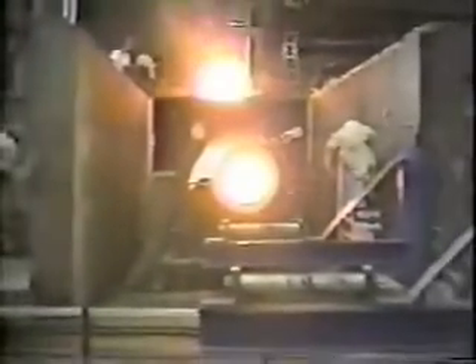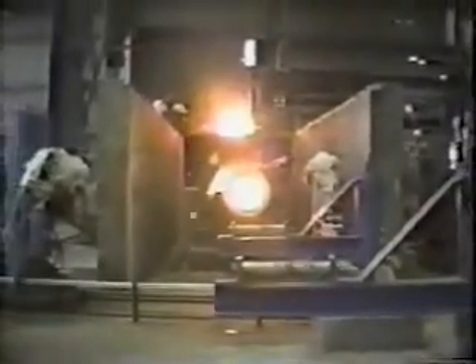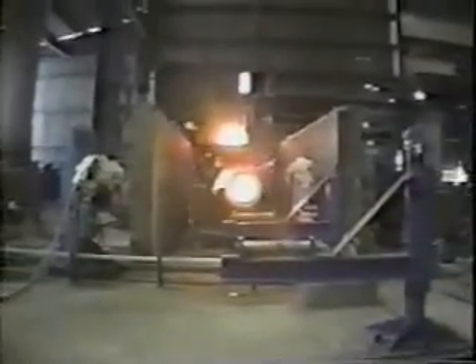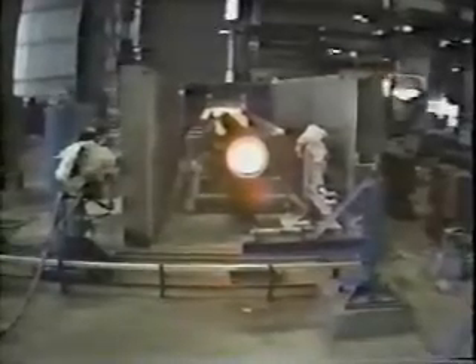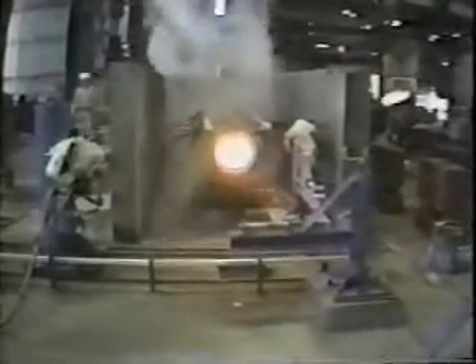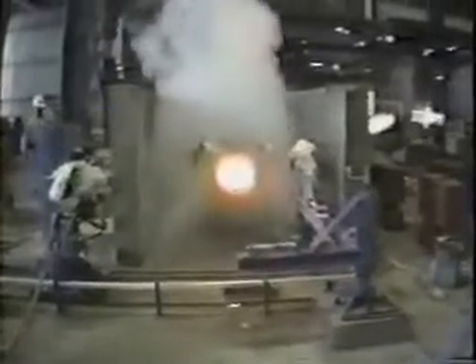The solidification begins on the outside diameter of the casting and solidifies progressively through to the center of the casting. The inside diameter of the casting solidifies last, providing directional solidification and elimination of any shrinkage defects in the casting. The proper timing and amount of water cooling can be developed for providing optimum quality and solidification time in each particular casting.